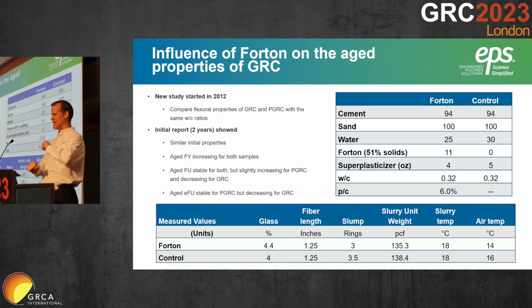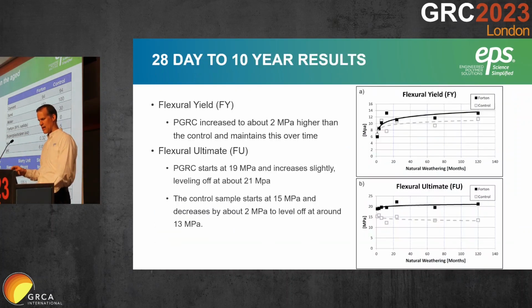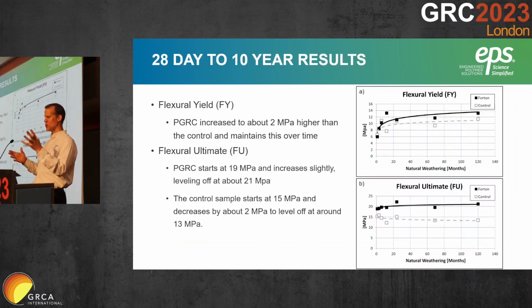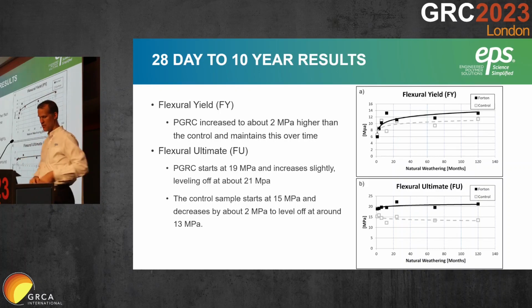To look at this, 10 years ago we started a project looking at GRC made with the same water to cement ratios, using Forton and using no Forton. 2 years ago we showed the results up to 24 months. We've got 10 years results in here now. You can see the Flexural Yield, both of them grow, with Forton a little bit more than without. The Flexural Ultimate, with Forton it's actually going up, whereas without Forton it's going down.